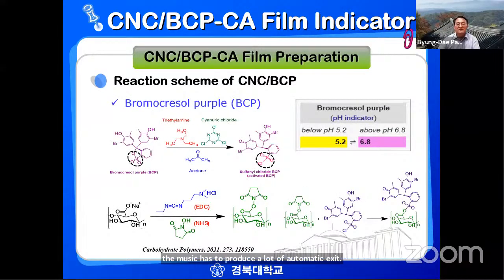And then we try to use the CNC, which is prepared by ammonium persulfate oxidation, combined with bromocresol purple in a cellulose acetate film as a kind of film indicator. As you see here, you have the bromocresol purple like this. We need to activate the sulfonic groups using the same method as previous: triethylamine, cyanuric chloride, and acetone, and we also use sulfonyl chloride BCP here. As you see, the bromocresol purple changes colors: below pH 5.2 it is yellow, and above pH 6.8 it becomes purple.